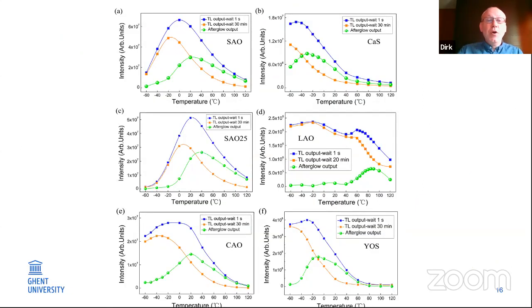So each time we can see the thermoluminescence measurements, the total intensity of thermoluminescence measurements as a function of temperature, the blue curves. Then after 30 minutes fading in orange, and the difference between the two in green. And there we can evaluate the optimum working temperature of these different phosphors. So for strontium aluminate, this is at about 20 degrees centigrade.